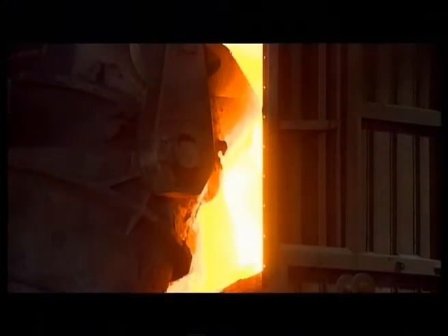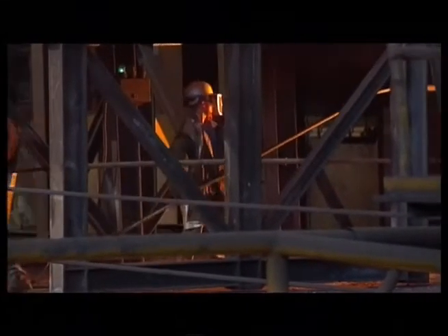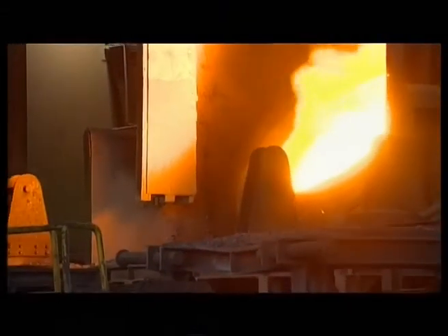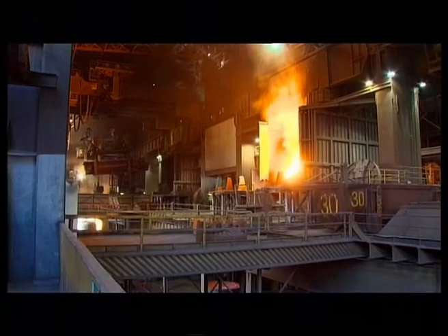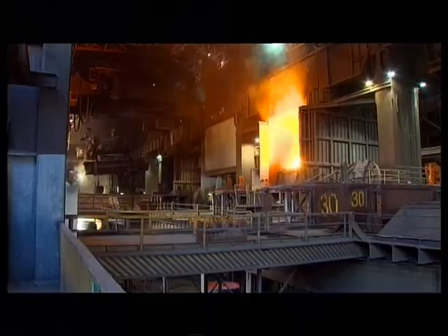This process removes impurities such as phosphorus, carbon, sulfur, and manganese from the molten iron. Some of these impurities float on the surface of the molten iron just like oil on water, forming a layer of slag which can be easily removed. About 300 tons of steel are produced here every 16 minutes.